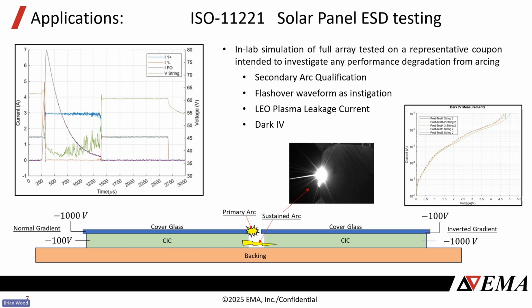But what can happen is that primary arc will happen right in between the gap between two strings. And now you can possibly create a bridge between those two strings, and depending on the voltage between those strings and the possible current that can be supplied behind that arc, you can form sort of a permanent arc across that gap. And so this was discovered early on, and since it's got such a high risk associated with it, people really want to investigate this.